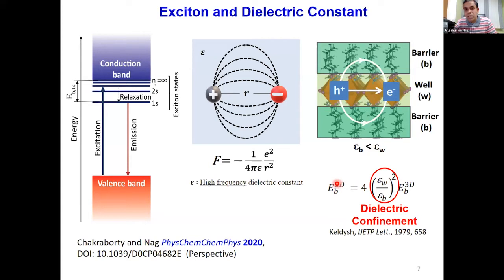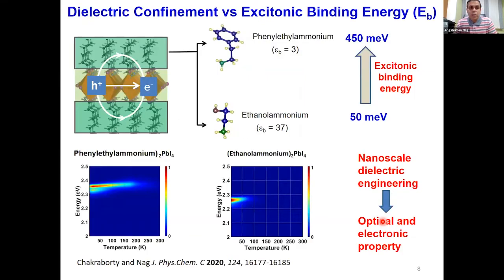So this is the excitonic binding energy, which reflects the Coulomb force between electron and hole. For a 2D material here, you see a term coming as a ratio. The excitonic binding energy increases when the ratio of the dielectric constant of the well, which is nothing but the inorganic layer, and the barrier, which is nothing but the organic layer here, increases. So this particular term increases the excitonic binding energy, and this particular term is what is responsible for something called dielectric confinement.